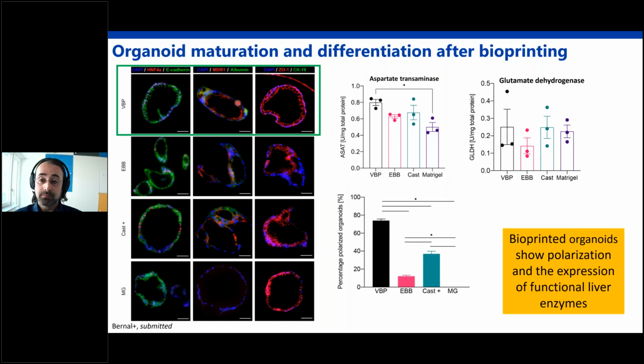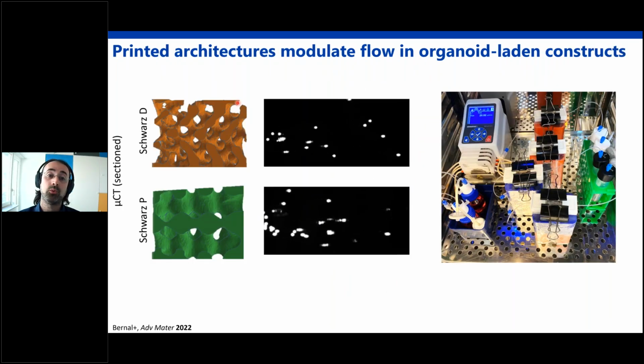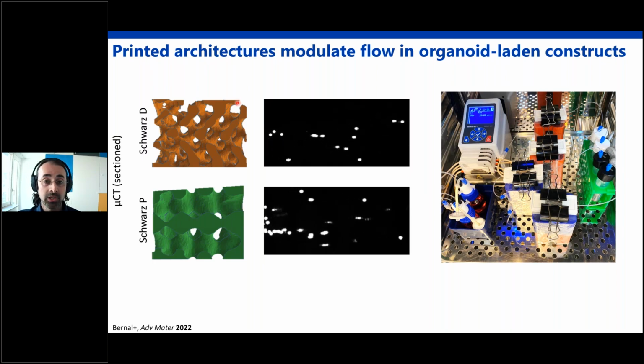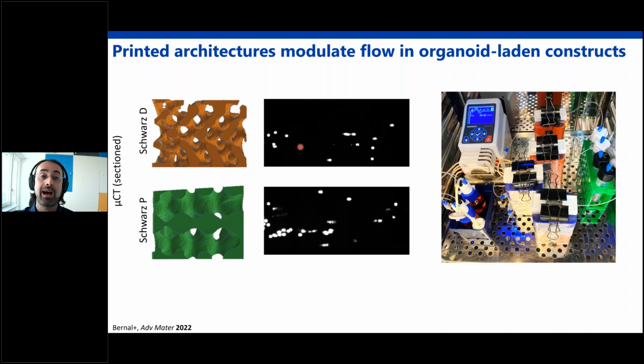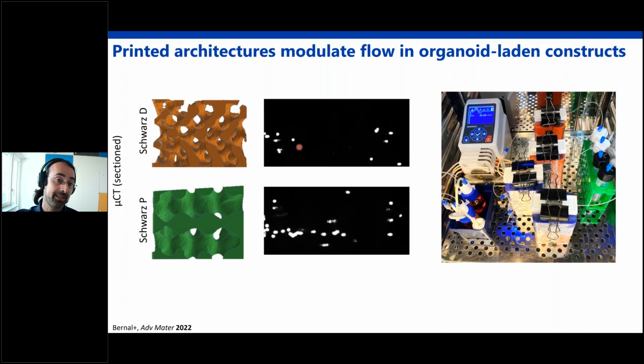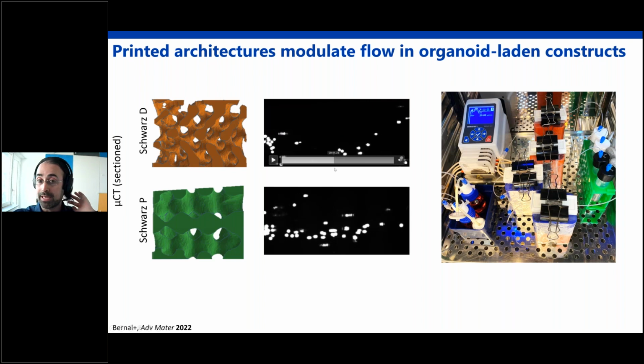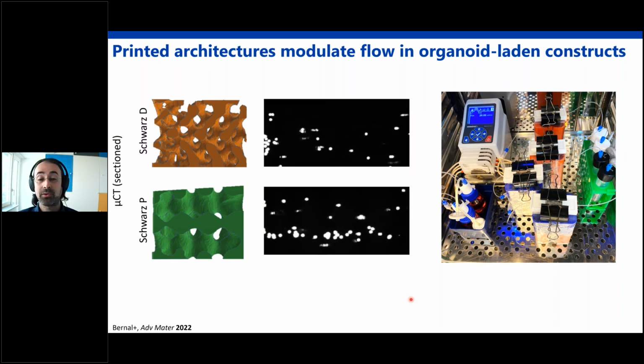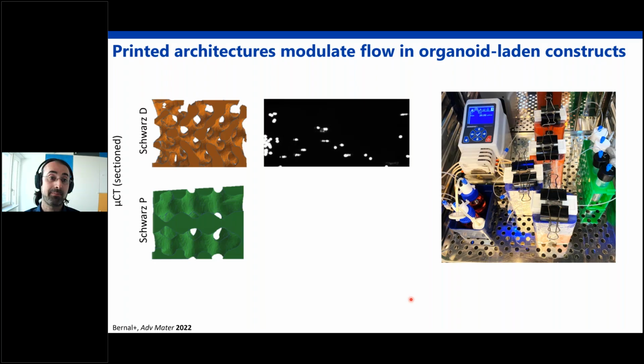We can then use printing as a tool to modulate the architecture around which we place these organoids, so that we can actually interfere with how the organoids interact with their surrounding environment. So now the cells are placed inside these two printed structures, which are here in a CT reconstruction. These are two types of gyroids, one with a very convoluted pore pattern, where you can see if we inject fluorescent beads into the pores, they follow a very up and down and tortuous path. And another one more straightforward, where the beads, if they're injected, follow essentially a straight line. So this way we can modulate the surface area, but also how much time these beads or the solutes in the media spend inside these gels.